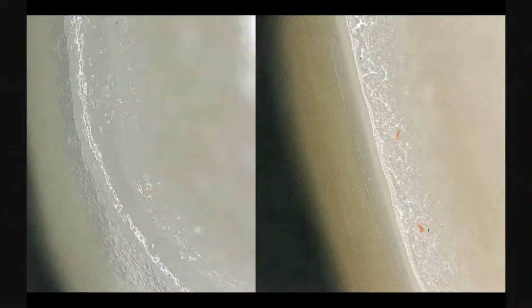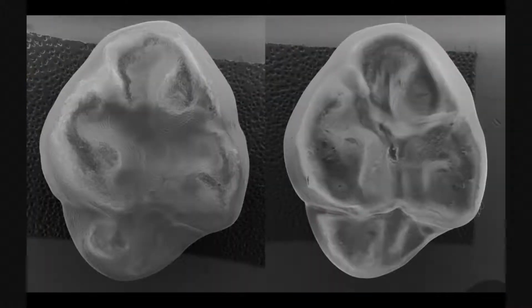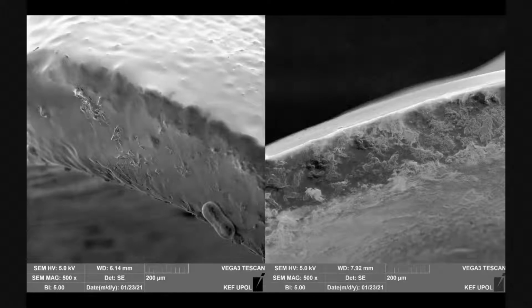Look at the margin. On the left side is the margin of the lithium disilicate. On the right side is the margin line of the permanent 3D printed resin. And another picture of the occlusal surface to better see the difference, how overmilled, because of the very thick pointed bur responsible for the occlusal surface, compared to the printing part. And again, the magnified margin under the microscope, with lithium disilicate material, where you can see the chipping on the external part of the margin line, and how smooth and sharp is the margin of the resin printed from the permanent material.